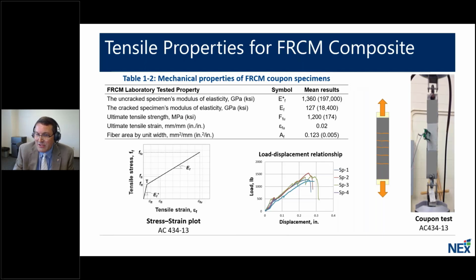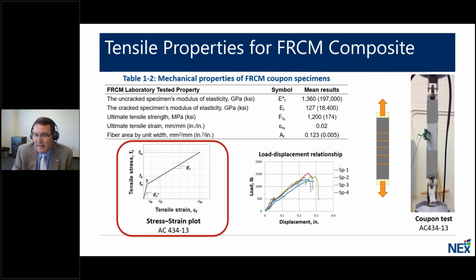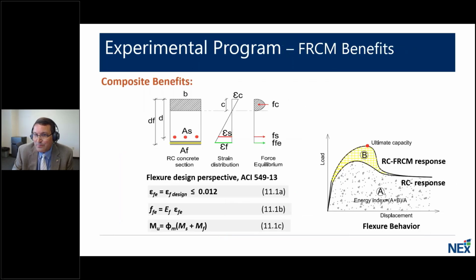In the direct tension test, there is a bilinear nature of these FRCMs as shown in the plot, and this includes a linear elastic behavior at this stage until the cracks actually form. Once the cracks form in the actual matrix, then it's the fiber that is carrying the load, of course. And the properties for the study are shown in Tables 1 and 2.